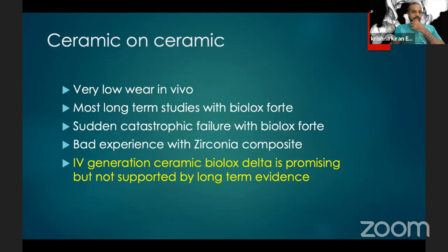We've seen that ceramic on ceramic is a very attractive option in young patients because of very low wear rates. But most of the long-term studies are with Biolox Forte, which is an aluminum ceramic, and sudden catastrophic failure has been reported with Biolox Forte. So a lot of people are skeptical about using ceramic bearings. And as I told you, we had a bad experience with zirconia composite.